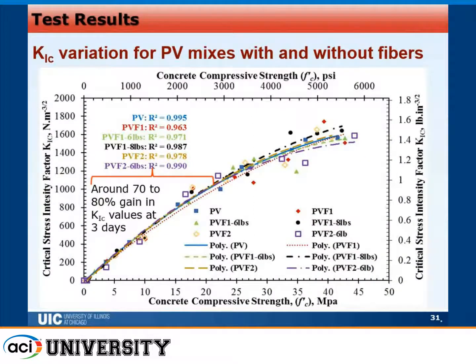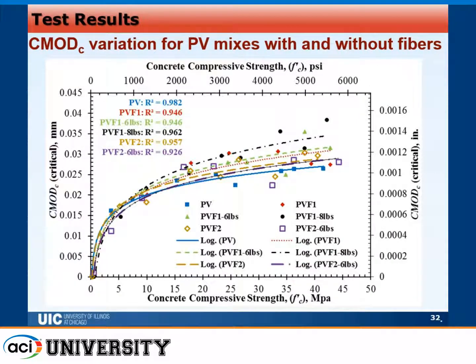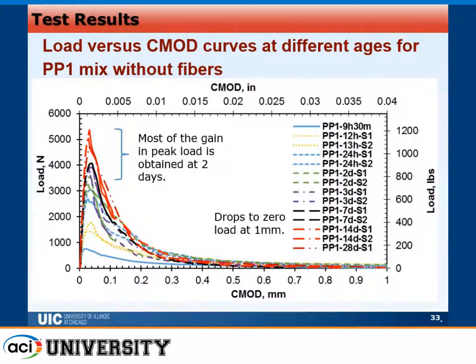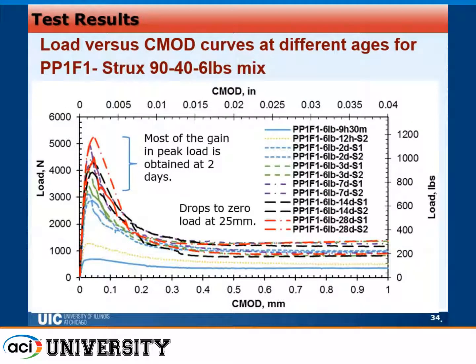The values for the stress intensity factor, also the variation of the stress intensity factor, were very consistent for all the PV mixes, with very high gain at around 3 days. And similarly for the CMOD values, at around 3 days, 70% or even more, 75%, was obtained in the first 3 days. For the PP1 and PP2 mixes, almost similar observation.